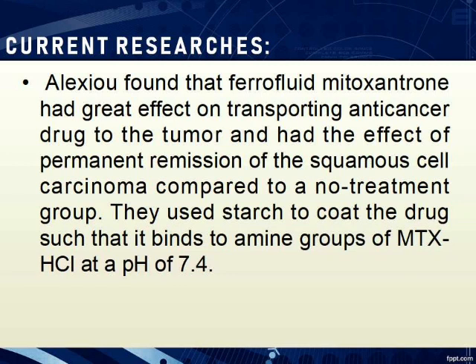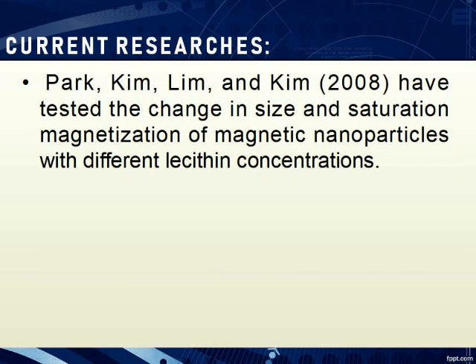Alexiou found that ferrofluid with mitoxantrone had a great effect on transporting the anti-cancer drug to the tumor and had the effect of permanent remission of the squamous cell carcinoma compared to a no treatment group. They used starch to coat the drug such that it binds to amine groups of MTX HCl at a pH of 7.4.